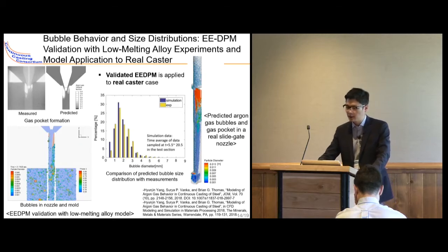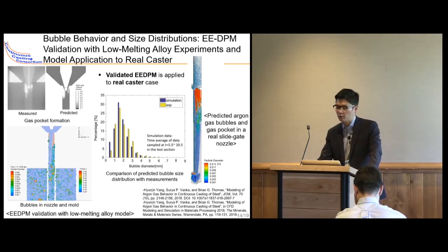Also, this EEDPM model was validated with the low melting temperature alloy experiments showing the gas pocket locations and size distributions. And then the validated model was extrapolated to calculate the real argon bubble behavior and the size distribution in the molten steel in a real cast nozzle.